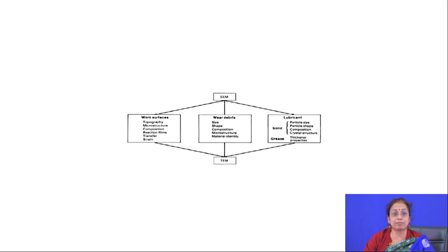As a result of which, it helps in reducing the wear kinetics. So the third-body particles which are forming at the interface are very important, and they give you information about the mechanism of wear. As a result, it is very important that after the wear is over, you collect the wear particles and then do XRD analysis to know the kind of particles that have formed, and to also infer information on the mechanism of wear. So this is what is shown here.